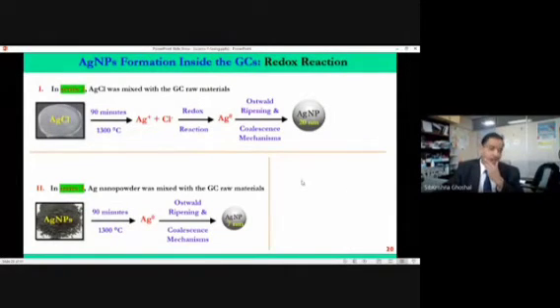So how does this happen? There are mechanisms. The mechanism is called the redox reaction, reduction oxidation reaction in chemistry. Basically, chlorine gives up 1 electron, silver is positively charged, so this electron is captured by the silver to form the neutral atom. Many neutral atoms join together to form the silver cluster, and this silver cluster we call a nanoparticle. But if we start with already pure nanoparticle from the company, again some of the bigger nanoparticles can break into smaller sizes. So basically the idea is to tune the nanoparticle size, that's it, because the surface plasmon property of the nanoparticle is dependent on the size and morphology.